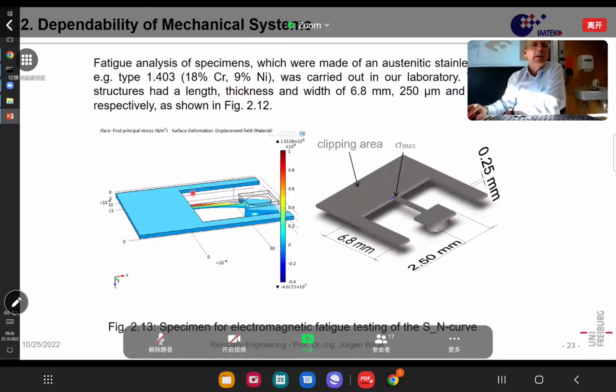But yeah, here we can see it. Here the maximum stress. We pull it down, press it down, and push it up just by that magnet which is put on here. But it is also important, what you cannot see, the amplitude was measured with an optical vibrometer. That was important because otherwise the stress would have been too undefined. So in that way, we had very small parts. We can see here it's only a few millimeters. The thickness of that part was only 1/4 of a millimeter in that case.